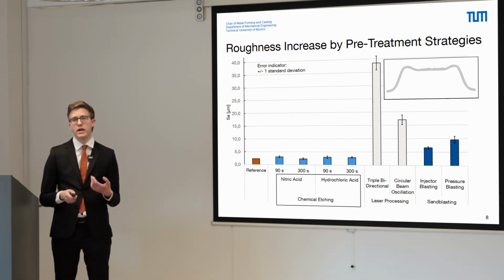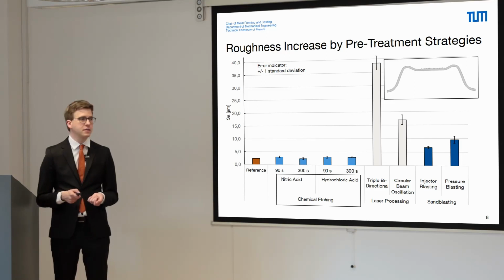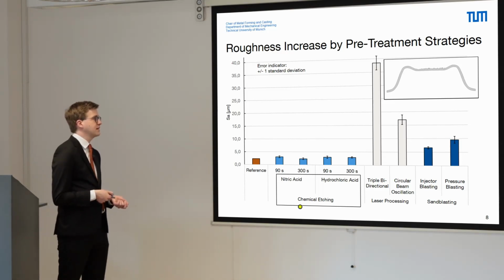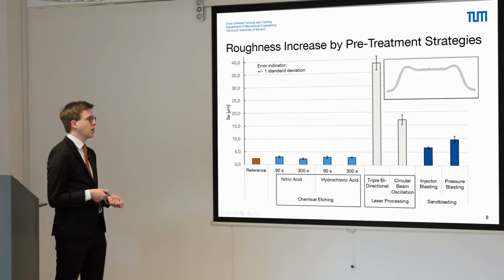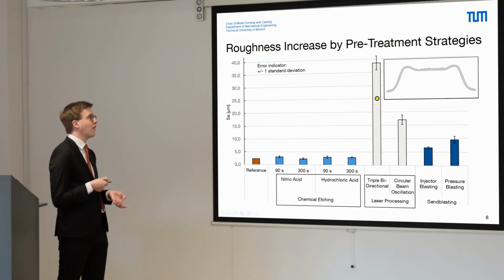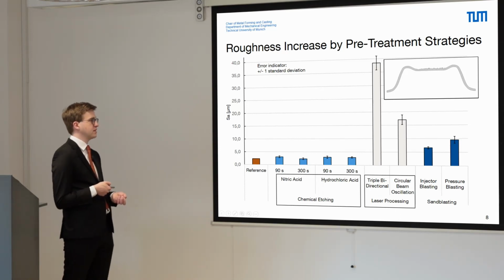So therefore, we examined two other kinds of surface structuring pre-treatments. The first is the laser processing using both a triple bidirectional pattern and a circular beam oscillation pattern. As one can see from these figures, the largest amount of surface structuring and roughness increase was achieved with the triple bidirectional laser processing strategy.